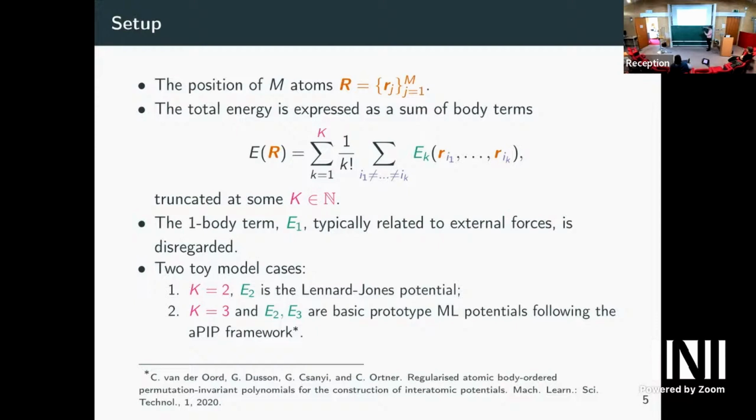That's all the two body terms; you iterate over all the pairs. Then if you go to three body terms, you basically have a central atom, and then you look at the triplets. For instance, in this case, you are perhaps interested in the distance between the central atom and the two other atoms and the angle that the three atoms create together. And then you can go beyond, to nth body order, in such a way.